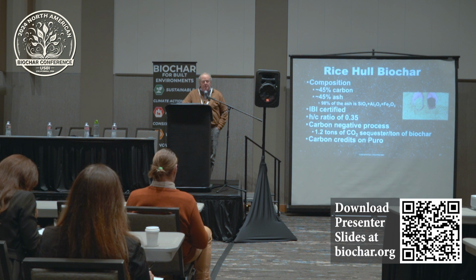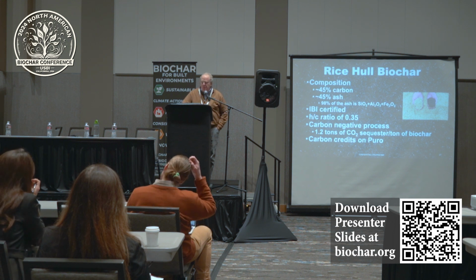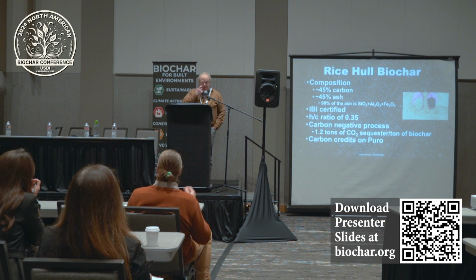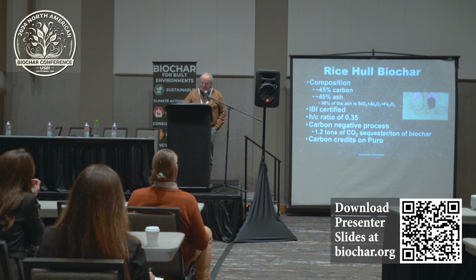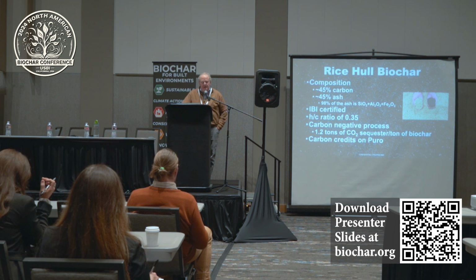A lot of people have burned them for fuel. It's not a great fuel because of the high silica content in them. So if you're burning them too high, you end up with glass in the furnace. You're burning them too low, you end up with silica ash. The silica ash has some potential applications, but it takes some management to be able to do that.